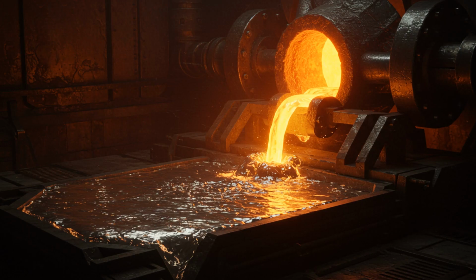This is the heart of the invention, the float bath. Imagine a long, sealed chamber filled with a shallow pool of molten tin. Why tin? Because tin has a high density and remains liquid at the temperatures where glass solidifies. The molten glass flows onto the surface of the tin like oil on water. Because the glass is less dense, it floats, and because the surface of a liquid is perfectly flat due to gravity, the glass takes on that perfect flatness.